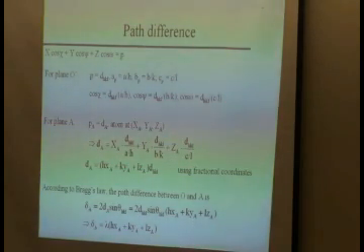And our P here is no longer P, but is the P_A or dA of that atom. Okay? So if we do that, the P becomes dA, the X becomes XA, and then for cosine of psi, I still use this expression, right? Because the angle won't change, never mind how far I go along that vector.